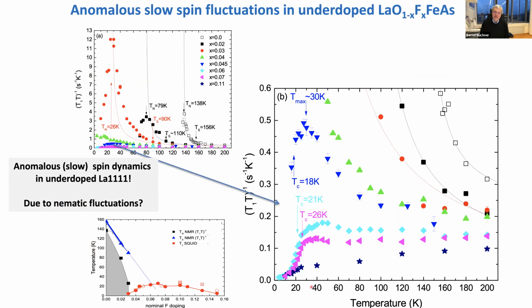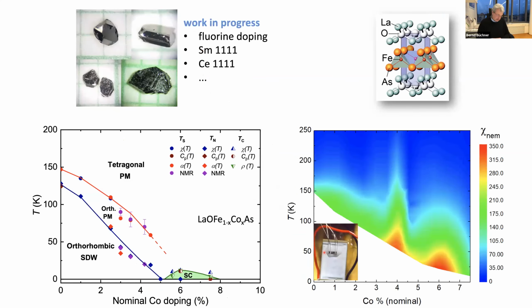Okay, these similar things you can also observe in these fluorine-doped compounds. We did this earlier already: you also have this very unusual relaxation with very unusual slow spin fluctuations. And I think it's now becoming clear that this is definitely connected to these nematic fluctuations, which are very soft in these optimally doped compounds. And only if you go to overdoped compounds do you end up with something which looks more or less like a usual metal. Okay, that is the first part.